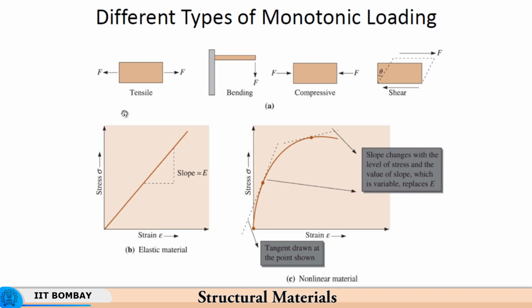That is because even if the stress rises to a very high value, a high slope in E ensures that the strain is very small. This becomes important because if you have equipment of, let us say, infinite stiffness, meaning infinite Young's modulus, then it will not deflect at all, which means that the machine elements will not change their shape at all. Now, although the strains are recoverable, so if the load is removed, the strain is completely recoverable, still the fact that the material is changing shape under load can itself create a problem over a period of time, and this is due to what is called fatigue.